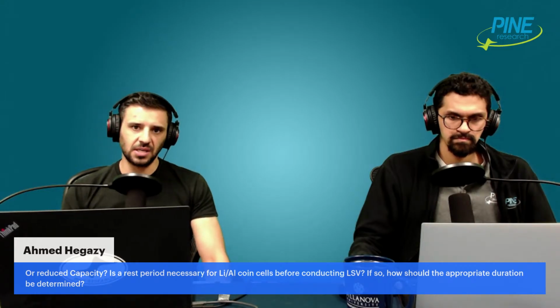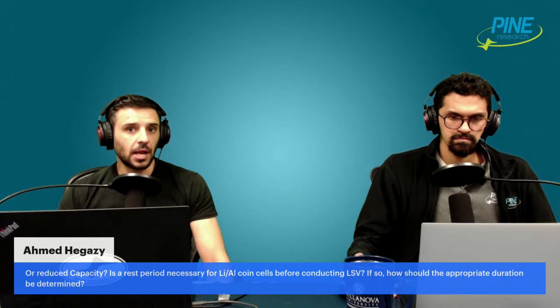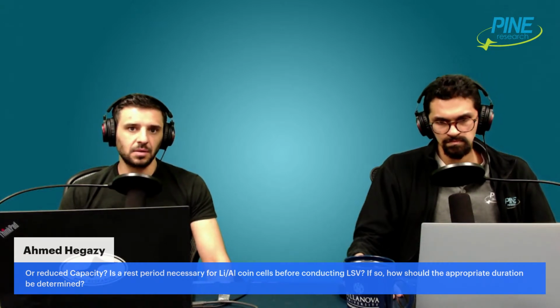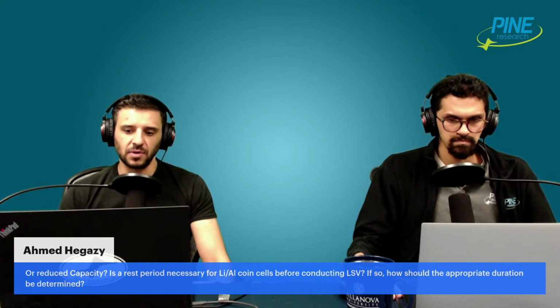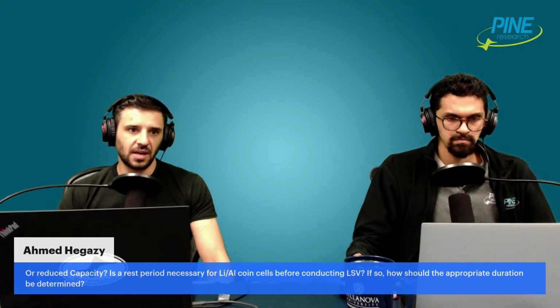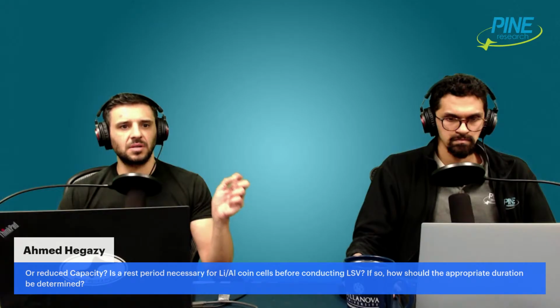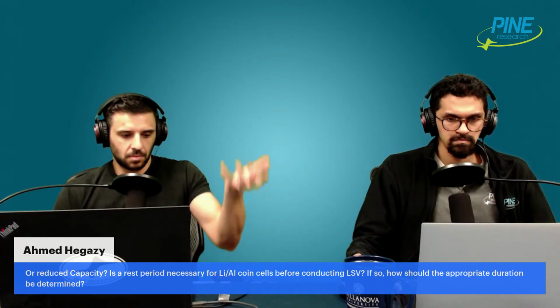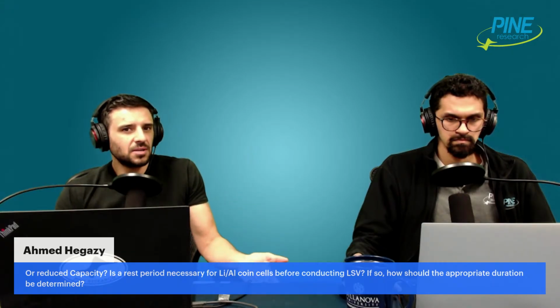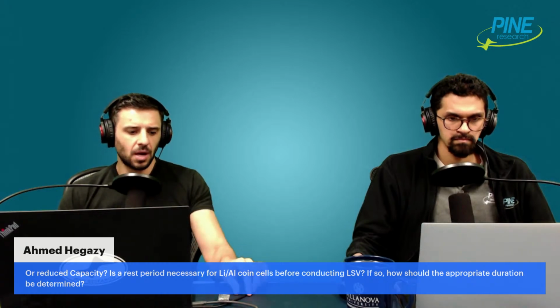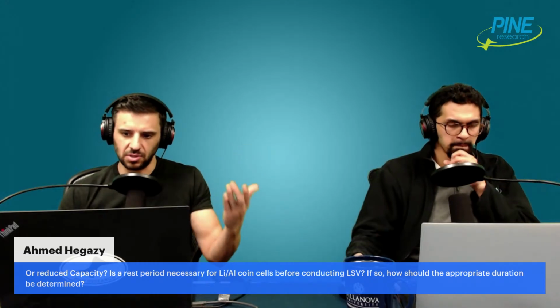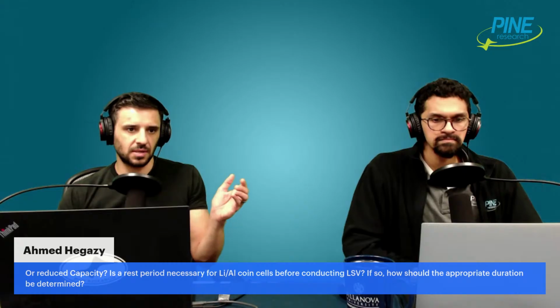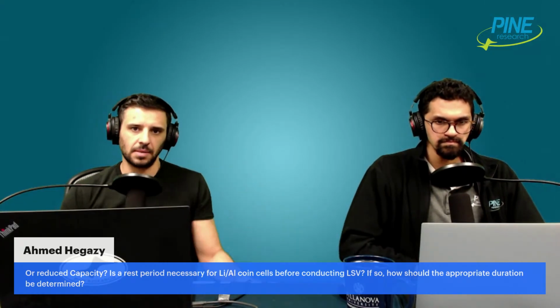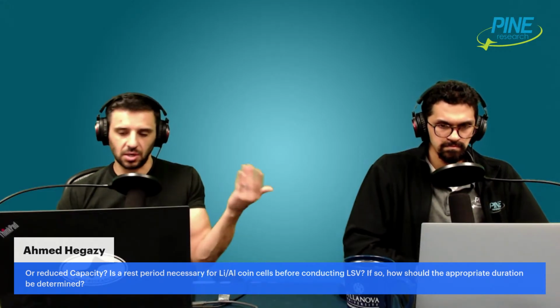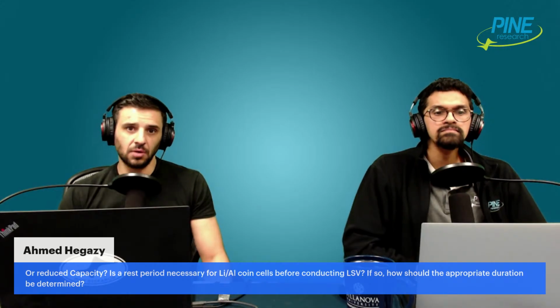In general, it's a good idea, when you set up an experiment, to run an open circuit voltage, open circuit potential, experiment for 30 seconds, 60 seconds, and just see that you have a stable voltage. If it's drifting like crazy, something might be off, or it's just taking a while to achieve a stable surface. But if you're working with battery materials that you are relatively certain are appropriate or will function, it's not usually necessary to let it sit for an excessively long time. You can usually start your first cycles, which is usually to form the SEI. Loading up one side or the other with lithium is sometimes the first step to get your battery in a state that it can start being charged, discharged. So I would say, as a general rule, yes.